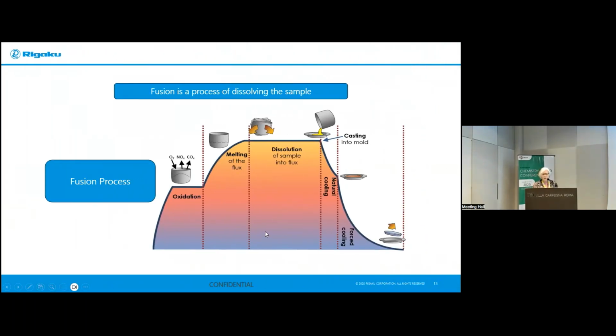Fusion involves the process of melting a solid sample, which is a powder, into a molten glass. The process involves an oxidation step where we get rid of volatile components like CO2, oxygen, and nitrous oxides, and all kinds of oxidation changes that happen within the material at a certain temperature for a certain period of time. The next step involves the melting of this oxidized or pre-treated sample into a flux, and then the dissolution, by introducing steps like the mixing, the cooling and the casting, as you can see per the diagram here.